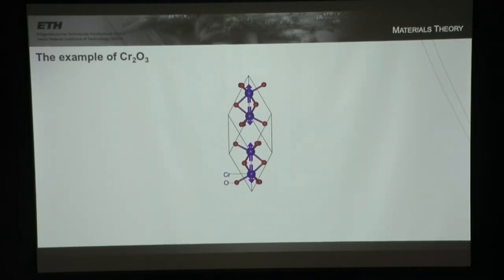But chromium-203 actually has ordered magnetoelectric multipoles, and I'm going to make two kind of cartoons to show you why. So the first one is, if I just look at this pair of magnetic moments here, there are two magnetic moments pointing out. I could rewrite that as a hedgehog pointing in and a quadrupole, right? If I add these together, I can see I end up back where I started. And then down at the bottom, I have the same thing. So just from this simple thought experiment, I might imagine that I have a bulk magnetoelectric monopole, a hedgehog, plus a bulk z-squared quadrupole in chromium-203. And this would be, back to the question, this would really be in the unit cell. This is like a macroscopic thermodynamic quantity.